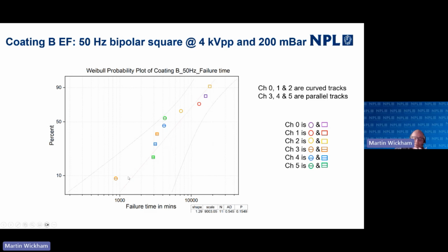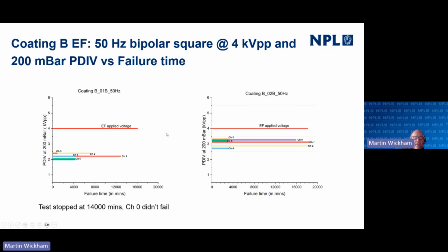So that's indicating to us that the opportunity for PD to occur is greater when you have a parallel track, because the field strength across that gap is over a larger section of coating, and therefore more likely to find defects in the coating and more likely to fail. Again, here we've plotted the same. In this case, for all our samples, the inception voltage was below the applied voltage, causing failure.